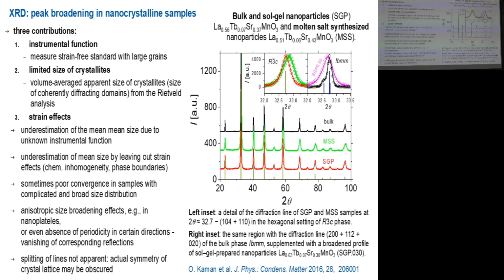And often the parameter that is calculated in this analysis, this parameter should be understood as some volume weighted mean size of coherently diffracting domains, and is usually denoted as the mean size of crystallites. By all means, you should not interpret this as some true size of individual particles. But it's a very representative value that is measured on a larger amount of sample, and there is no space for user bias, and it is volume weighted. It is somehow accurately defined, so it's nice.